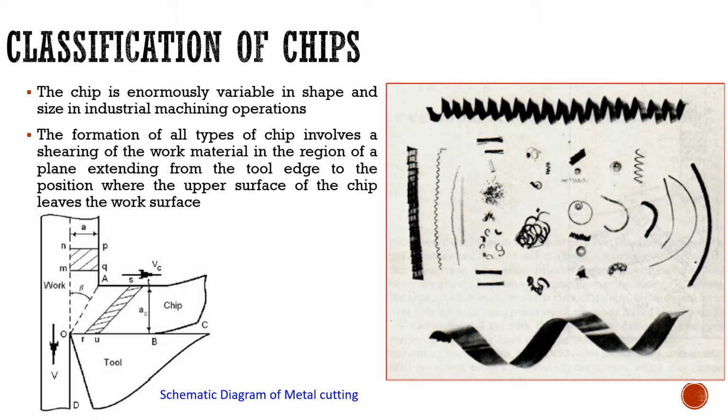This can be evident when the work or tool is touched, by the presence of temper colors on the chip, work, or tool, or it can be seen in the loss of hardness of the tool point, with loss of tool geometry and failure due to excessive flow at the cutting edge.